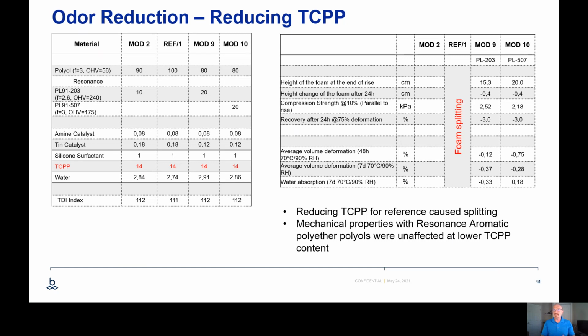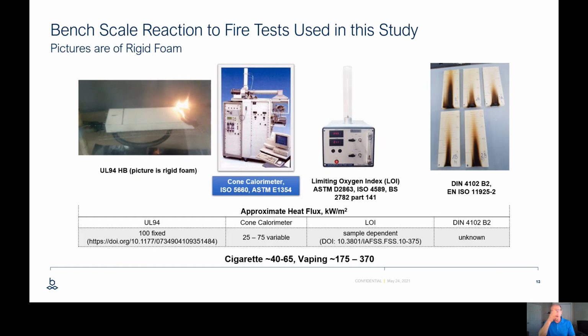So we were able to cut some samples for at least reaction to fire testing, but we were struggling with the material splitting, as opposed to our materials, which did not exhibit splitting for those systems. Now we have to test reaction to fire, and being new in the system, I have done work with flexible foam. I wasn't sure exactly which would be the most reasonable reaction to fire test to choose.